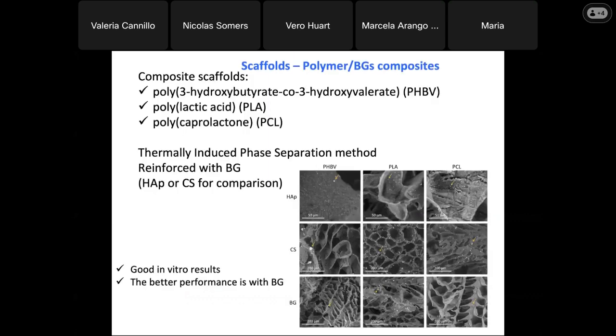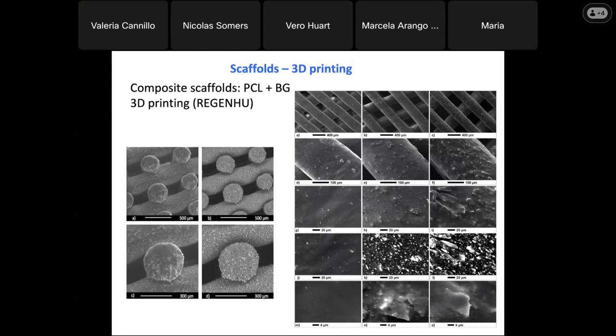Then we also produced composite scaffolds, using different polymers such as PHBV, PLA, PCL. And these scaffolds this time were produced by the thermally induced phase separation method. Such scaffolds were reinforced with bioactive glass, but also with hydroxyapatite and calcium silicate for comparison. We obtained good in vitro results, and the better performance was obtained with the bioactive glass. So this is very good. Still for these, we have only in vitro results and still need to implant them in rabbits. We produced composite scaffolds also using 3D printing, so a different technique. And here are the results also of the microstructure.